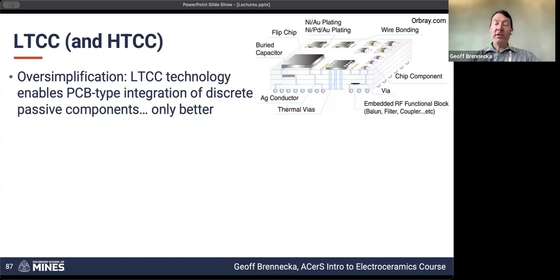So the reason I loop this in with the MLCC capability is because a lot of these layering, tape casting, lamination, and alignment sorts of techniques are used all over again for LTCC. So the vast majority of these, the LTCC component is called low temperature. It still requires sintering at 750 degrees C. So it's not super low, but that's low compared to what it would be for pure alumina. So these are generally alumina based, and they have been engineered with some liquid phase glass additives so that we can sinter these things at reasonably low temperatures.